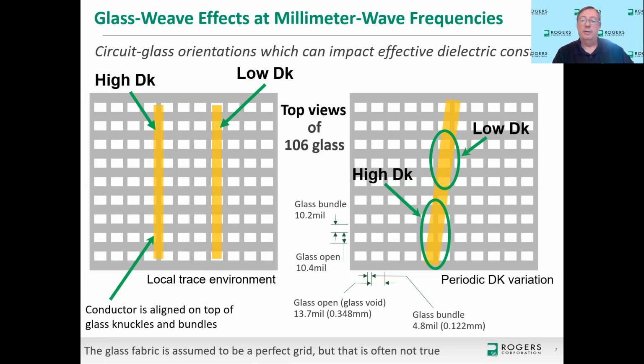But really what the idea is here, I'm showing the glass weave as a perfect grid and a signal conductor on an angle in respect to this glass weave. And in one area I have pointed to, there is high Dk. The conductor is aligned to the glass such that the conductor is over areas of bundle, knuckle, bundle, knuckle, bundle, knuckle. So it's a higher Dk region. And then as you move up farther, you get to an area of the circle that says low Dk. Now you're in an area where the conductor is over the glass in such a way that it's open bundle, open bundle, open bundle. So it's a lower Dk. So what you get is a zipper effect for this conductor along the length of the conductor that's high Dk, low Dk, high Dk, low Dk.